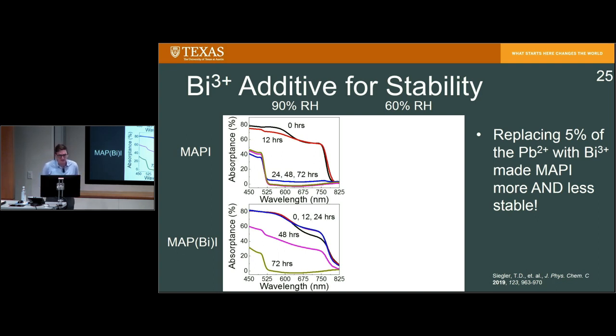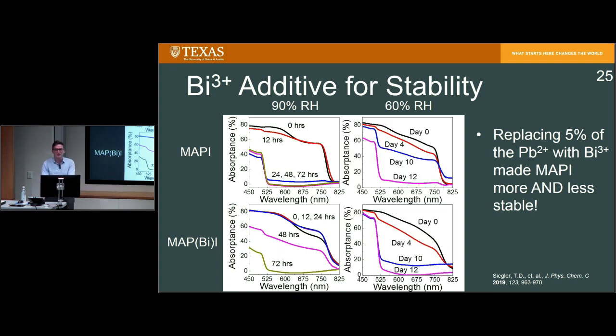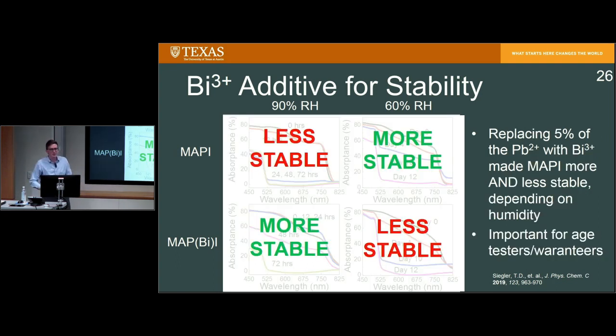This is telling us the bismuth has stabilized the perovskite by about a factor of 3 at high humidity, which is very promising. But then we took that down to 60% relative humidity, did the same test, and we saw the opposite effect. This stabilizing and destabilizing effect was the first report of its kind in the field.